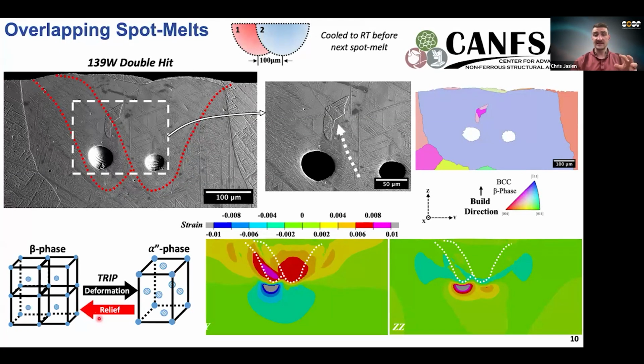But then when you apply some amount of stress relief, so in this case, a reduction from the thermal cycling, it actually relieves the strains enough that it can perfectly transform back into the beta phase. So our models were able to validate our hypothesis based off of looking at this structure.